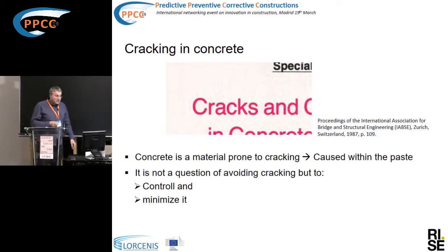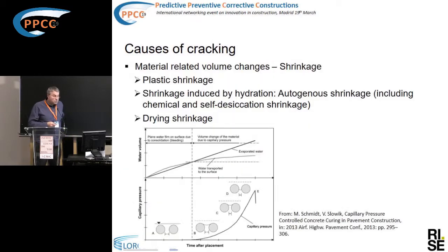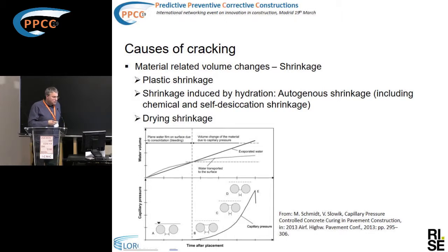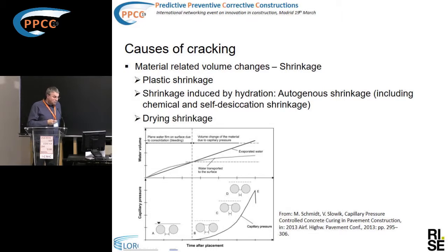Cracks are caused by a multitude of reasons, and one important reason — as Sarah also pointed out — is the material. This is actually the composite character of concrete: the binder material is prone to cracking. We have early, very early cracking in the plastic stage, which is called plastic shrinkage, or which can be caused by plastic shrinkage.